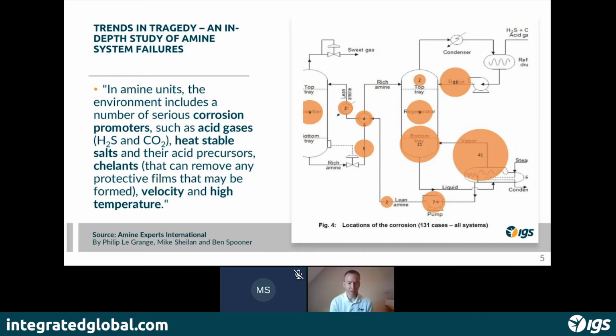So depending upon whether you have a CO2 stripper or an H2S stripper, in a CO2 stripper your oxide layer or your passive layer on the surface of the steel is going to be iron carbonate. That's a relatively fragile material. So if you have high velocities or medium velocities, you have any type of entrainment or impingement on the surface, you'll remove that oxide layer, creating an erosion corrosion cycle. And as you remove more of the oxide layer, if you don't have a good filtration system, then you further accelerate that process.